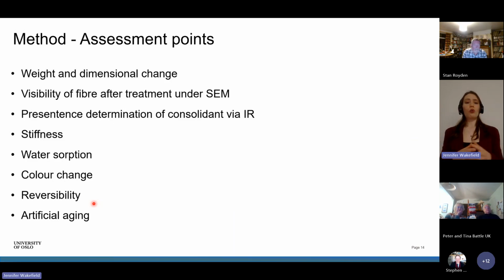And then, so we had to find ways of assessing the results. So we're looking at weight and dimensional changes. The weight changes are more to assess the variability within the spraying method and between the different applications, and looking at the dimensional change of the material as well. Then looking at the visibility of the fiber under SEM, to see can we still identify the fiber under the SEM, or would the consolidant interfere with that?